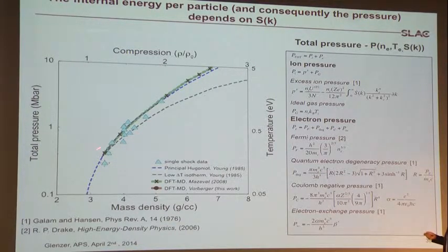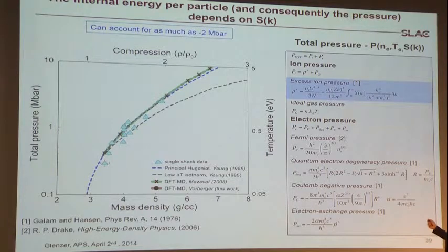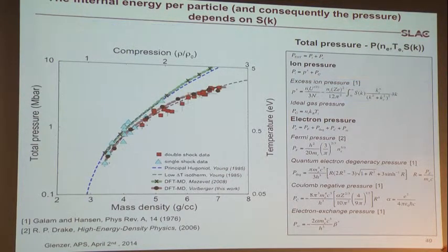And the only reason why we can derive pressure now is because all of these quantities that go into pressure calculations are measured. In particular, the ion excess pressure is a central quantity. Namely, you see there's a structure factor in this equation, and that structure factor is measured. And that can account for as much as 2 megabar. And once we include this, we can derive the pressure from our data. So now let's look at the data when the two shocks are colliding. Now what we find is that our experimental data follow or approach an isotherm. What that means is, as the shocks are coalescing, one can get to a higher density than in a single shock case.